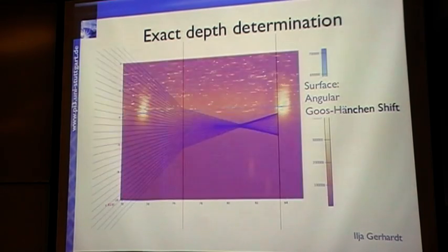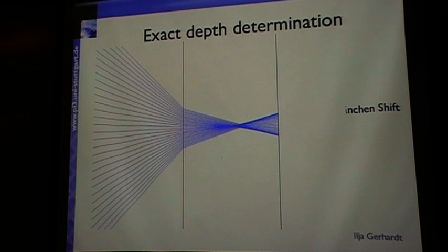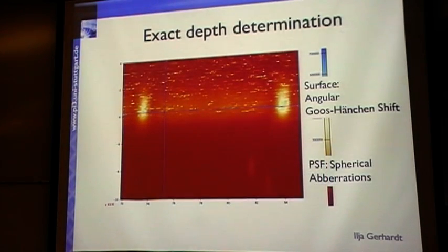And of course for the point spread function down there, at the NV center, we have a lot of spherical aberrations. For example, this is just a perfect lens on the left-hand side, and then there's a slab of diamond, and you immediately have a kind of variety. Even in ray tracing, it's not a tiny point where you can say, well, this is my focus. So here we have a lot of spherical aberration, and we have to fit or make a super resolution also in Z, which is not super easy.